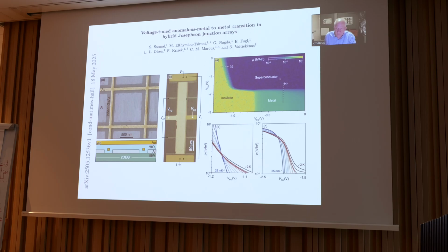The superconducting phase, when everything is all connected, characterized by a zero global resistivity. And then you can make transitions either into the superconductor insulator transition by depleting this frame gate, shown here, that shuts off the coupling between and produces this anomalous metal phase that we studied. Or you can, with the top gate, leave the metal between and create just a metal phase in 2 dimensions